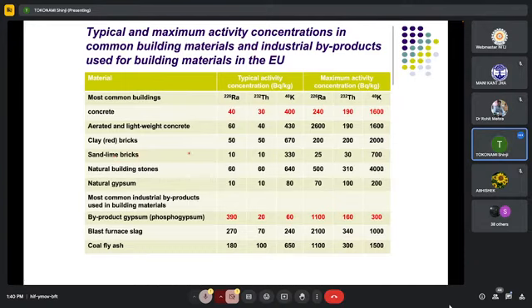Sand-lime bricks. This is lower than other common building materials. 10 becquerel per kilogram for radium-226, 10 becquerel per kilogram for thorium-232, 330 for potassium-40. Even as maximum activity, 25 becquerel per kilogram for radium-226, thorium 30, and potassium-40, 700.